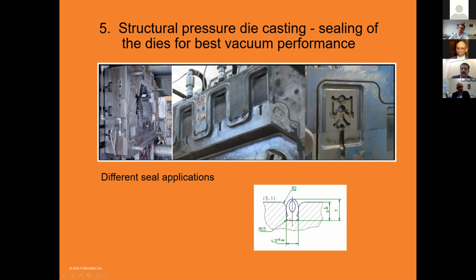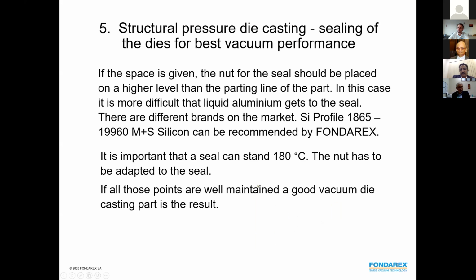The groove can be quite easy to make with some radius so the seal doesn't get damaged, and basically the seal itself holds into the groove, which is about 6 millimeters deep. So here I say in some cases maybe the seal should stand up to 180 degrees. The profile is 1865, which we use most. The DIN norm 19960. That's from Emmenegger.